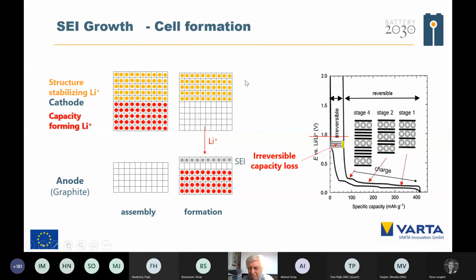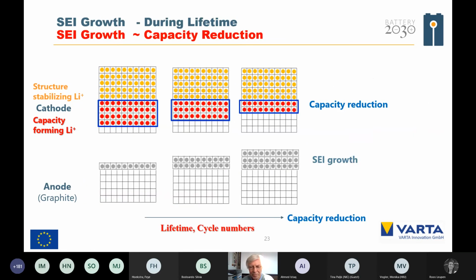And if you are looking at the first charge, so that is the empty graphite electrode. You charge it, you come down, and then you go back to discharge that one. You have here the so-called irreversible capacity loss. And that irreversible capacity loss, that is the SEI formed during the formation. But during the lifetime, because that is a chemical reaction, and I mentioned that layer is growing independent of charge-discharge, so we get a larger and larger SEI, and that means in parallel a capacity reduction.